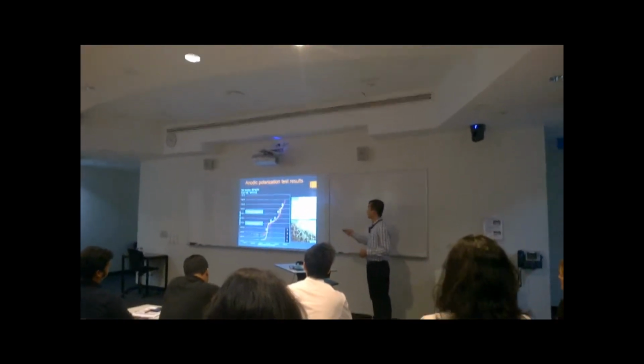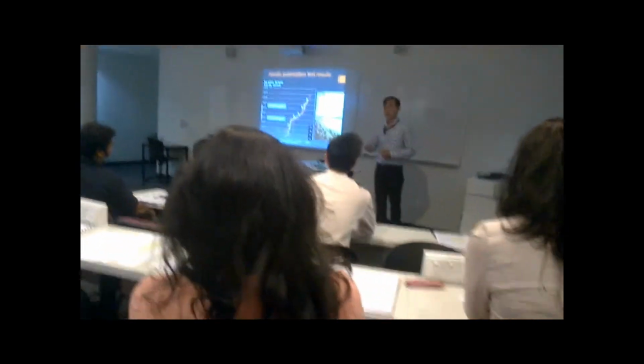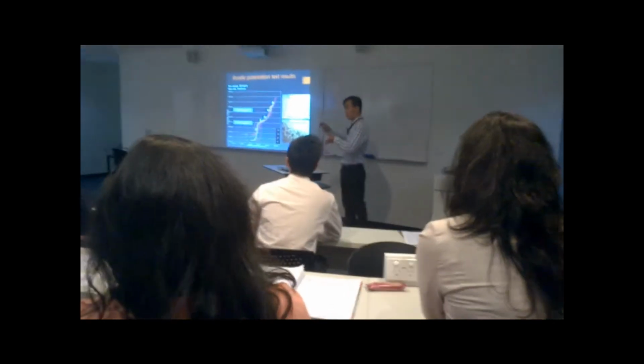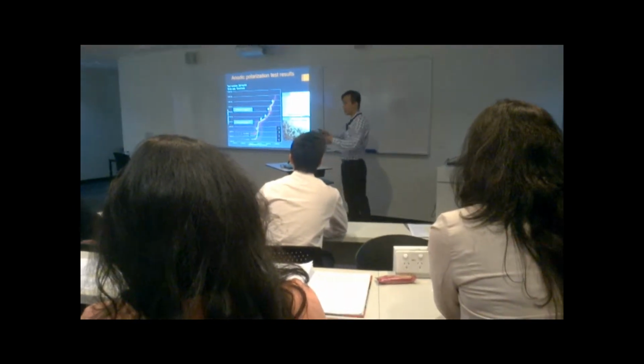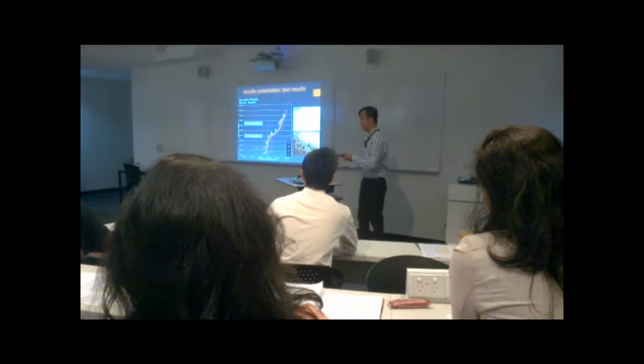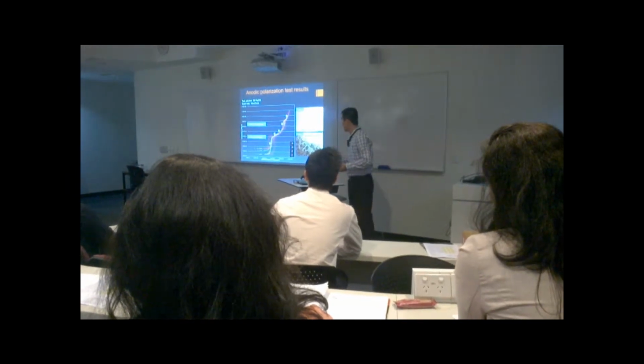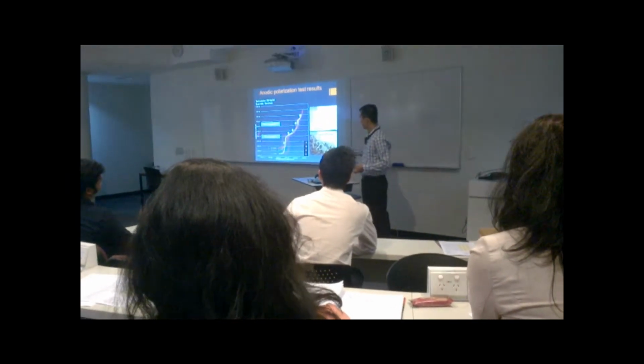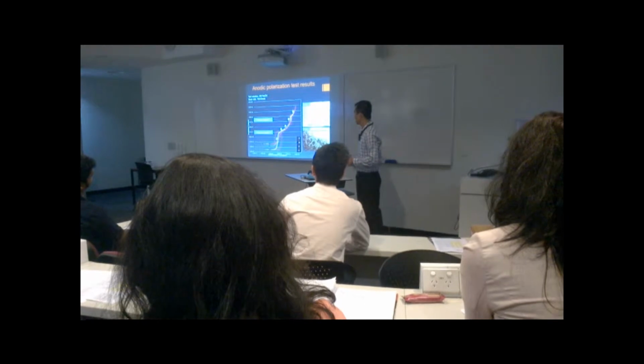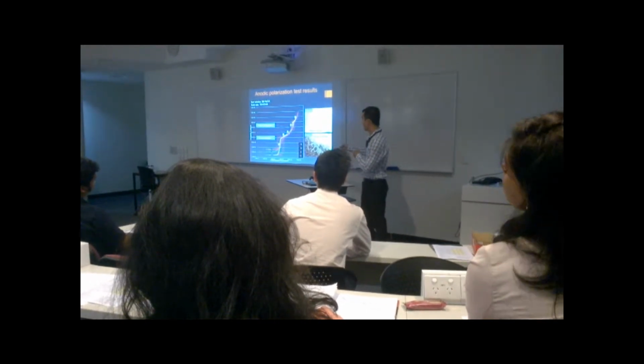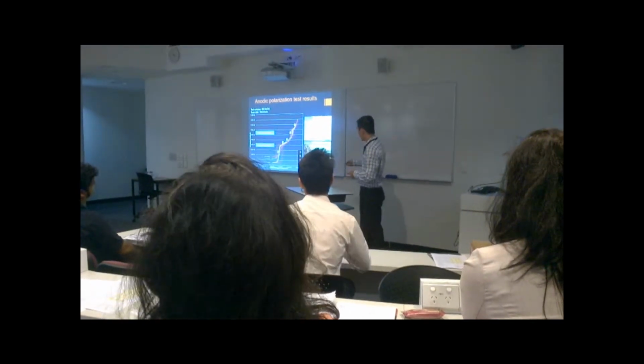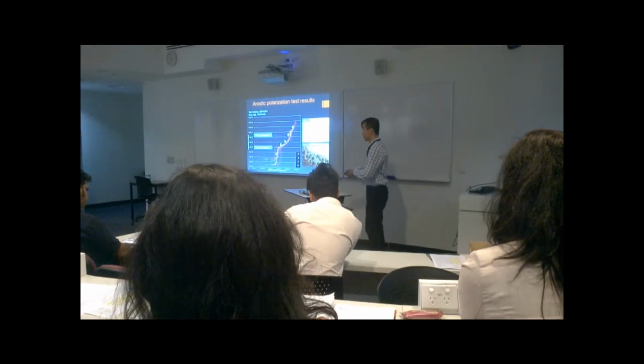So now we will have a look at the test result for the anode polarization test. In the anode polarization test, basically you apply a potential to the samples and you measure the output current. The higher the output current, the higher the corrosion rate. In the graph on the slide here, the vertical axis is the potential applied to the samples, and the horizontal axis is the current density measured out of the samples.